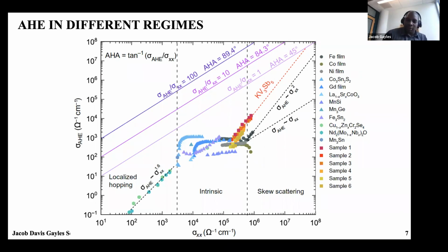Yeah, it's not completely clear, I think. This first one you see is from Tian, this PRL that says you can rescale this. These iron films actually is 2. It's not linear here. You also have phonon contributions that have a contribution to this scattering part, but I think it's not very clear why it's exactly 2. But I think you can say for sure, it's a log plot, right? So there's definitely not a 1. This is just iron, and this is directly from the anomalous Hall effect review. I'm not exactly sure how this linear scaling ever came about, but I don't know of any material that actually shows a linear scaling properly instead of a square law.